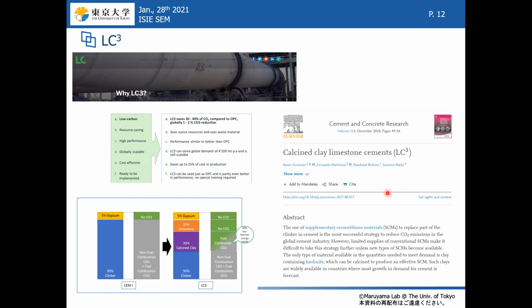So I would like to introduce several recent activities in the society. As I mentioned, Professor Karen Scrivener from EPFL recommends using calcined clay limestone cements, as clay is quite a general material found in many countries. The calcined clay and the limestone can be used as additives for cement. Since the amount of ordinary Portland cement used is reduced, this is a sure and favorable pathway to reduce CO2. But it is very difficult to stop the CO2 emission because this technique still requires ordinary Portland cement.